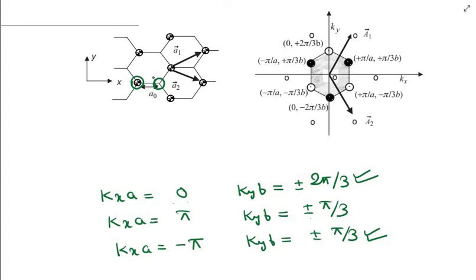So I would not say that there are 2 lattice points inside the Brillouin zone for which the band gap is 0, but let me reframe the statement, because one unit cell only contains one lattice point. A better statement would be that there are 2 inequivalent K points inside the first Brillouin zone for which the band gap is 0.